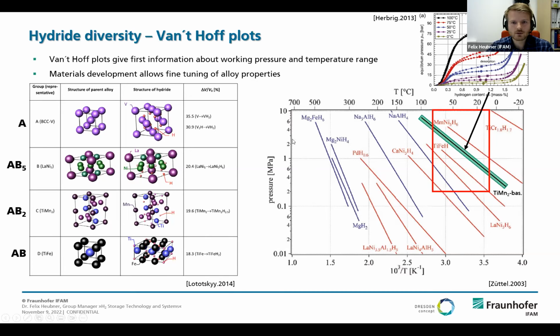So I already told you that temperature and gas pressure are always different for the different hydrides. And this is what the graph here on the right-hand side shows you. It is the temperature of operation and the gas pressure for the different materials. We have here one example, these titanium manganese-based hydrides. Behind this curve, that's a van 't Hoff plot here, stands a pressure composition temperature diagram.